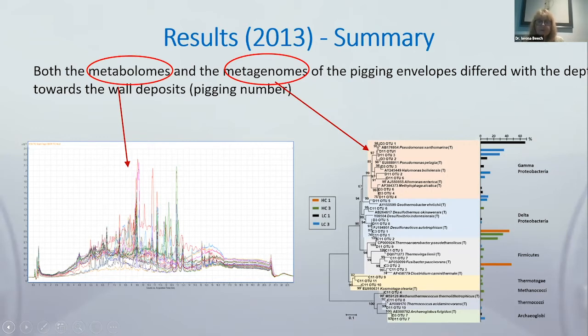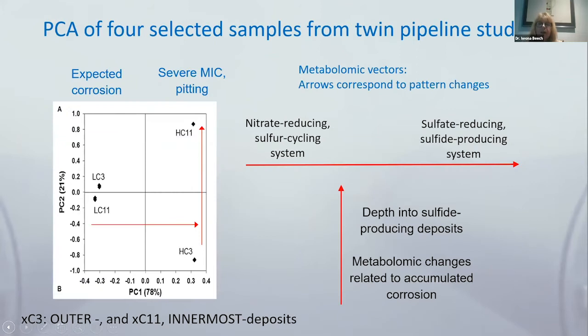Hence, what I've been doing for many years is taking samples from different depths, be that biofilm on steel piling for low water corrosion, the situation with the pigging, or any other, always core samples, always trying to dissect them and then compare the populations closest to the surface, because if there is action occurring, it occurs at the surface. It's not 10 centimeters away, although there are some transport phenomena that may facilitate corrosion from the top down, but typically we should focus on these interfacial processes. Very important information could be lost if one homogenizes the samples and does not sample from the surface.